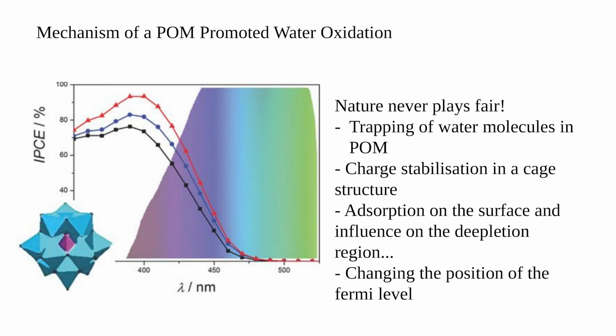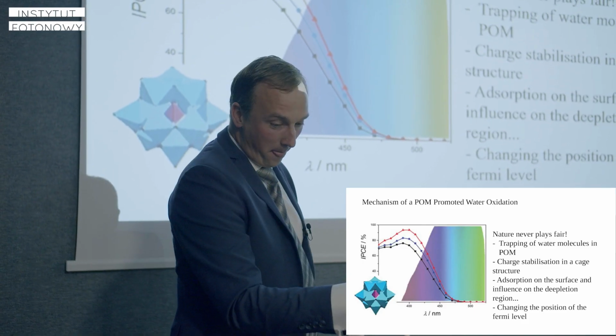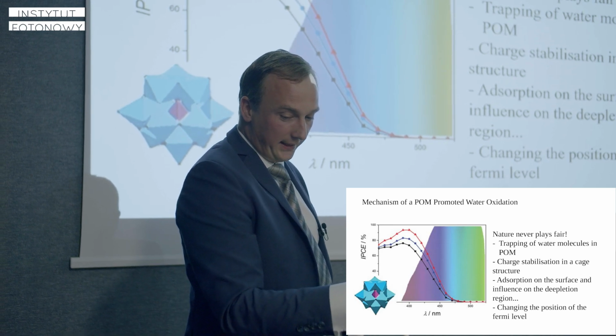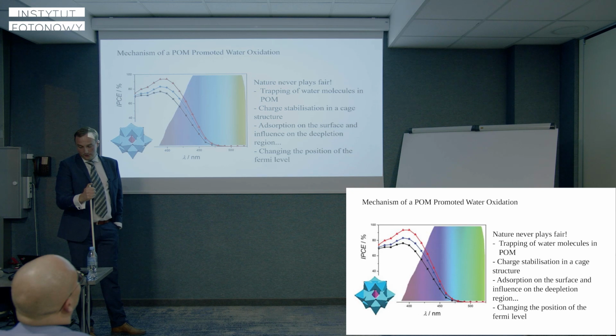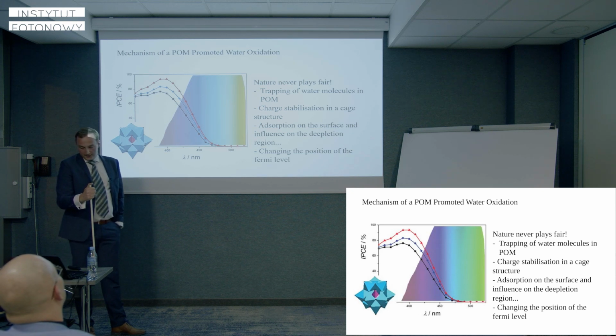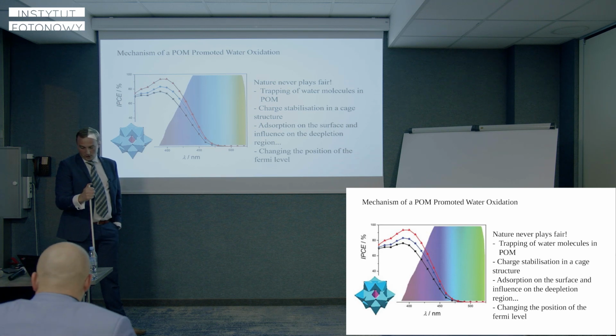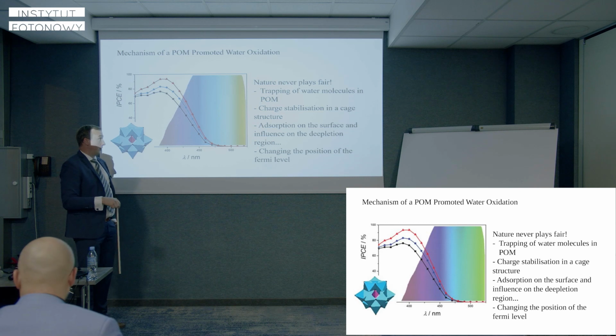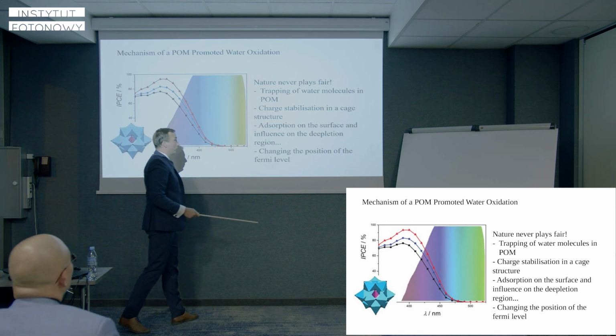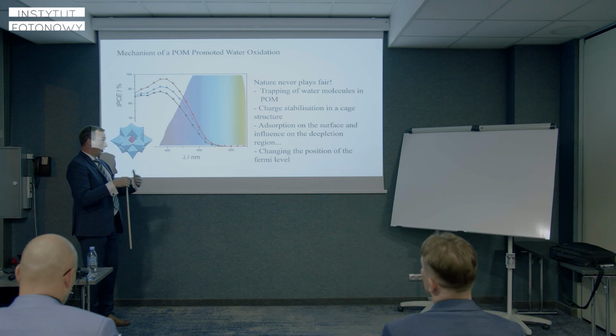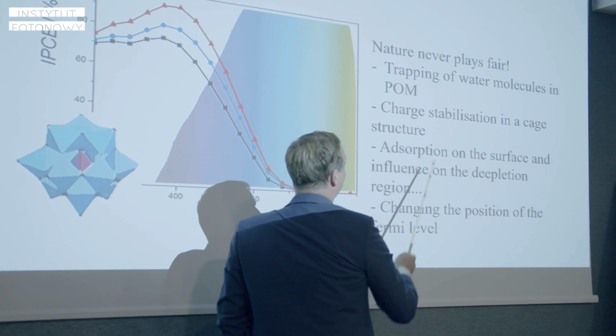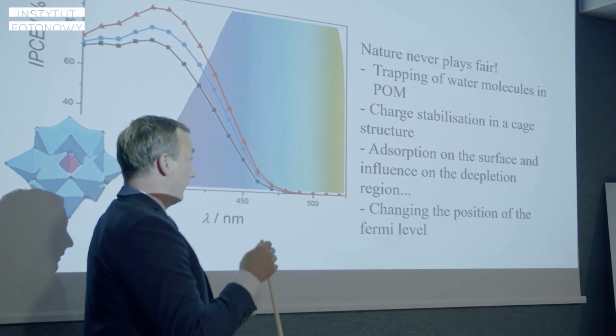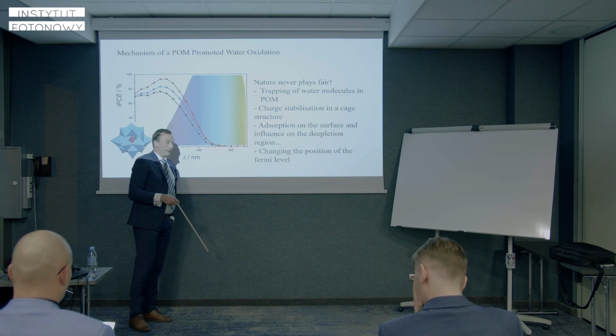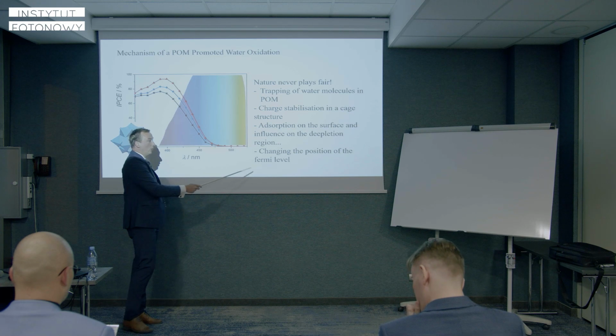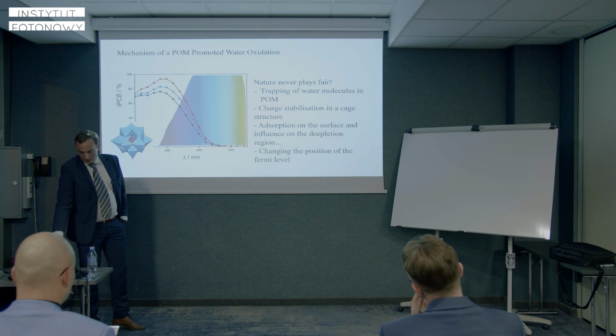Okay, so in conclusion, I can say with clear consistency that nature does not play fair. And explaining the effect of POMs on water oxidation is much more complicated than we thought when we started working with them. So we have defined at least 4 main directions for the influence of polyoxometalates on photooxidation. The first one is trapping of water molecules in the polyoxometalate cages. The second one is charge stabilization in the polyoxometalate structure. The third one is adsorption on the surface and influence on the depletion region of the semiconductor. Also, polyoxometalates change the position of the Fermi level.